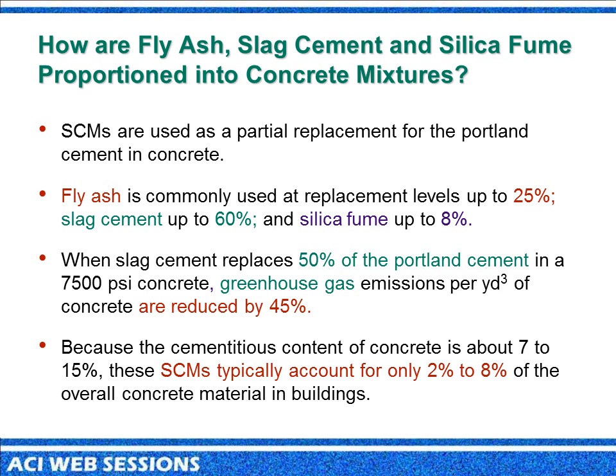In a typical concrete mixture, we can see fly ash used up to 25% on an everyday basis, and certainly slag cement up to 60% or silica fume up to 8%. Now, typically at 8% we see workability issues, and in other areas we have to balance this with our construction methods.